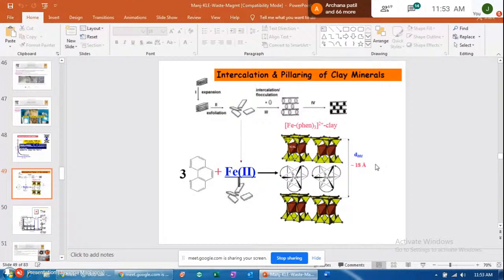I take clay, ferrous clay. I put a certain chelating agent, I just grind it, and I am able to do some solid state reactions. I don't have to put it in solution, heat, nothing. Simply by grinding, there is something called intercalation. So intercalation of this chelating agent takes place, and the Fe2+ gets complexed, and I can see the layer expansion by X-ray diffraction. I am able to see this basal spacing increasing.